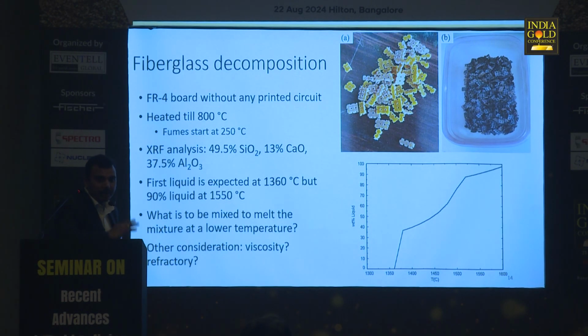Then we have this software called FactSage, which has thermodynamic databases and can calculate how this thing will behave if we start heating at high temperatures. So on the y-axis is the fraction of liquid. So if you take 100 grams, how much liquid will be there as you heat it up. The x-axis is temperature, from 1300 to 1600. So up to 1360, there is no liquid. Then you start getting liquid, but you have to go as high as about 1550 or so to get sufficient liquid. So that is very impractical if you want to process a copper-containing melt. You don't want to go to 1500, 1600 Celsius.